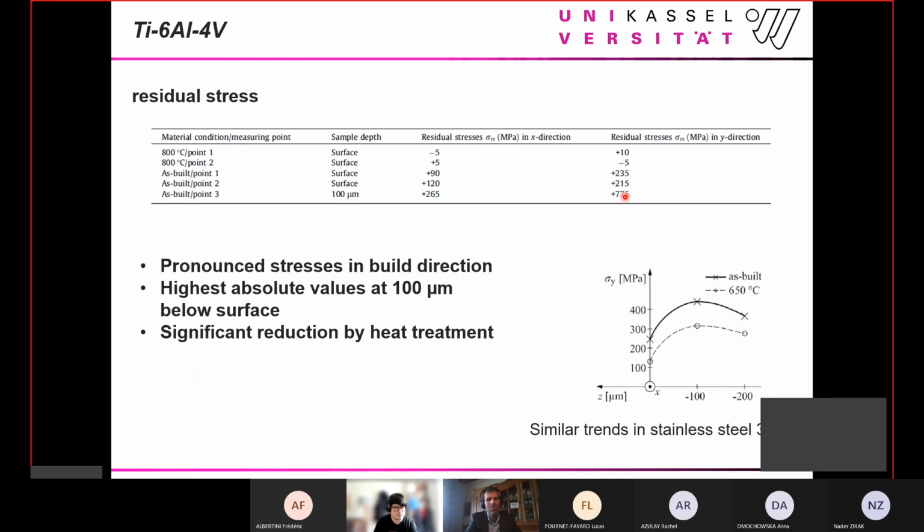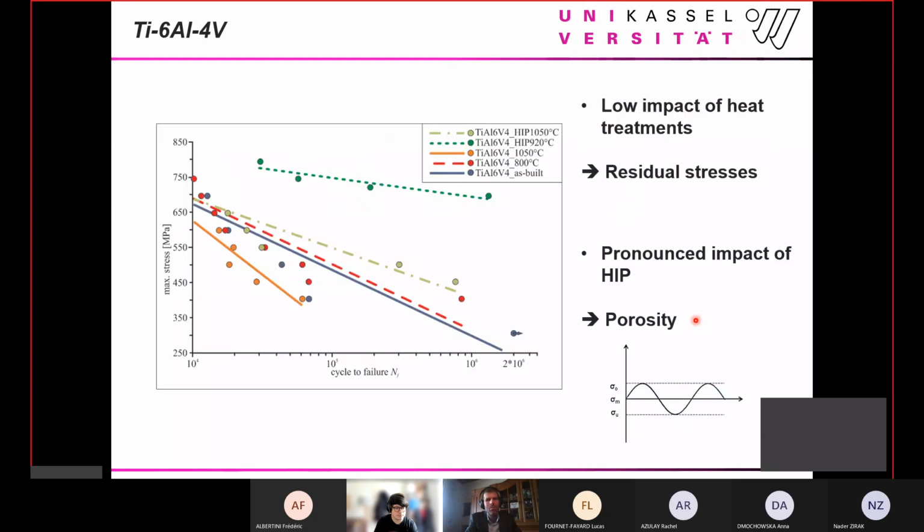So really detrimental for any kind of application. So we have extremely high residual stresses, and those high stresses are not directly at the surface, they are below the surface somehow, as is shown here for, in this case, 316L stainless steel. So we have to look at distinct points to really get to know what is the absolute value we encountered after processing. But I will show that this is not that simple to really do a critical assessment of residual stresses, at least in structurally complex components.